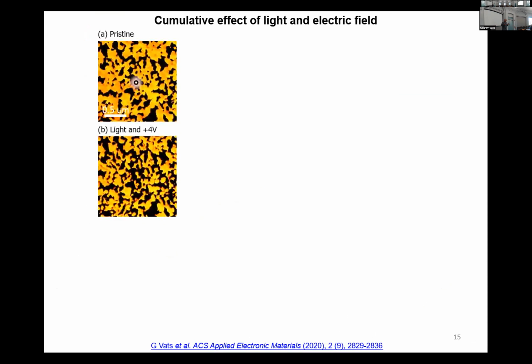Now let's look at the cumulative effect of light and electric field. I previously mentioned that there is an analogy between the two. This is very interesting, and let's see the first result. Again, I acquired this image. This is the pristine image, bright and dark domains, two types of domains. Then after acquiring this image, I put my AFM tip somewhere here at the center. You can see this white dot here. My AFM tip is around 30 nanometers in diameter. And if you look at the scale, this is like a 2 micron by 2 micron area.